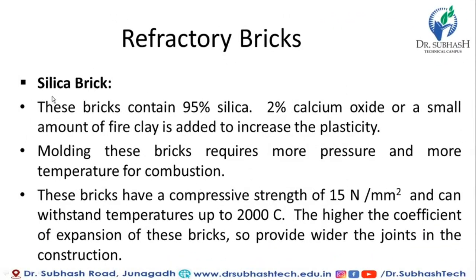Silica bricks are the next type. These bricks contain 95% silica and 2% calcium oxide, with a small amount of fire clay added to increase plasticity. Molding these bricks requires more pressure and higher temperature for combustion. These bricks have a compressive strength of 15 N/mm² and can withstand temperatures up to 2000°C. Due to the higher coefficient of expansion of this brick, wider joints must be provided in the construction.